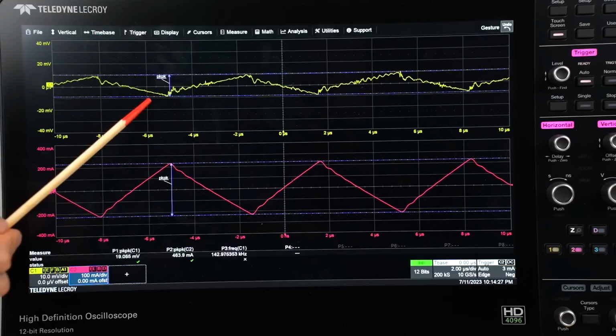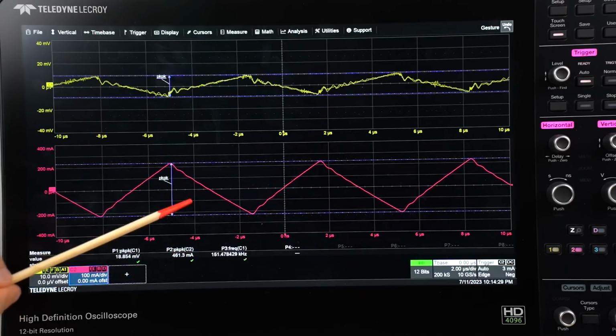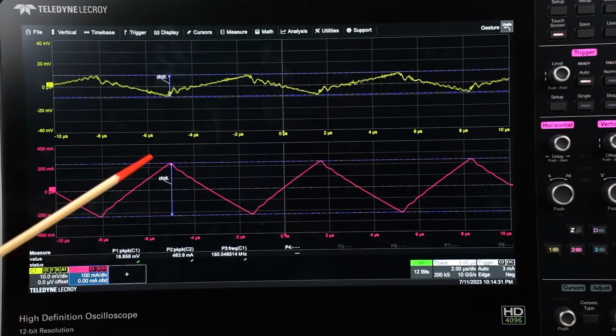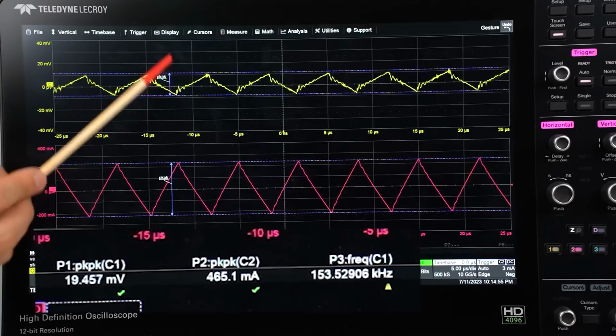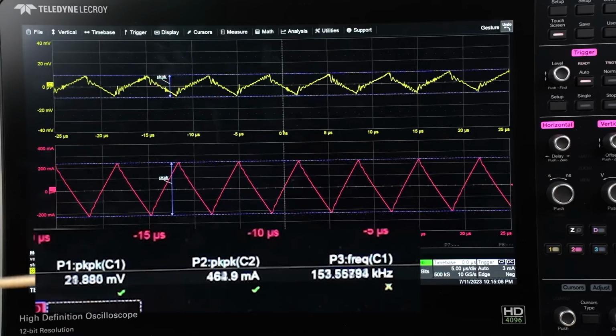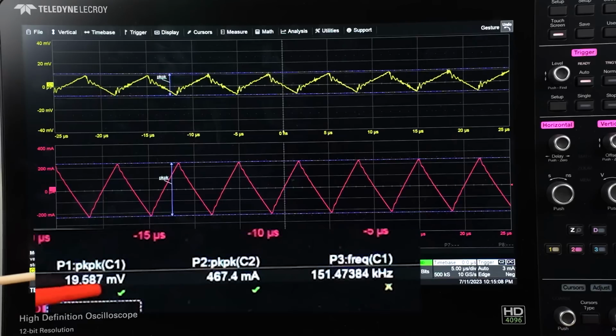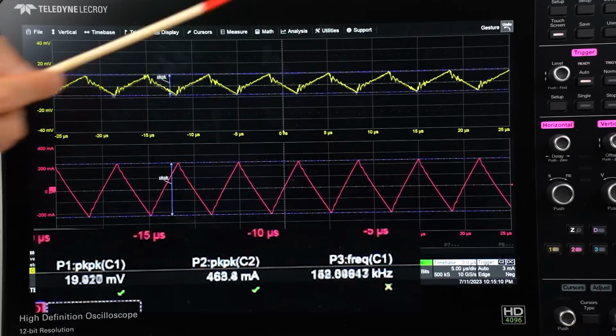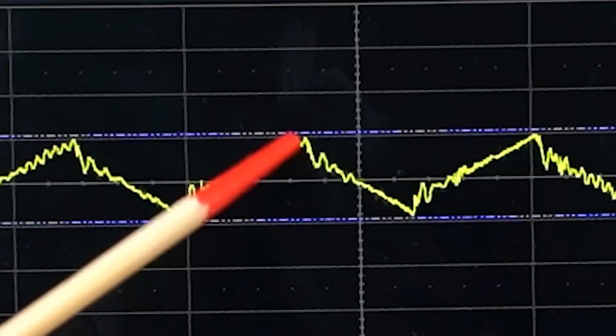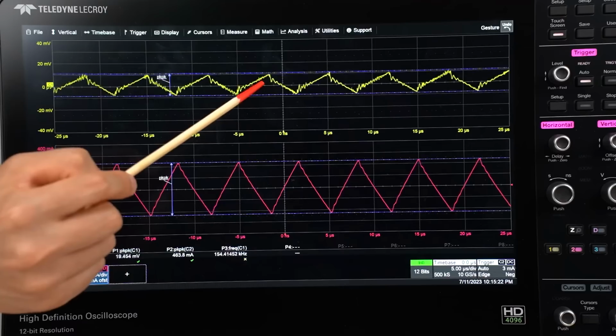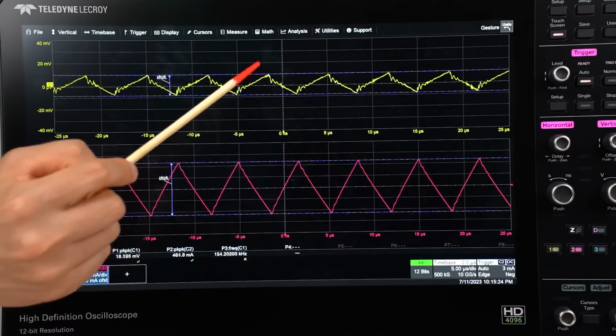The top waveform shows the ripple voltage, and the bottom shows the current flowing through the capacitor. The switching frequency is 150 kHz. The ripple voltage is approximately 20 millivolt peak to peak. I think it's pretty good. Since the capacitor has some ESR, there is a slightly sharp drop in here. You can clearly see the voltage caused by ESR at the point where the polarity of the current is reversed.